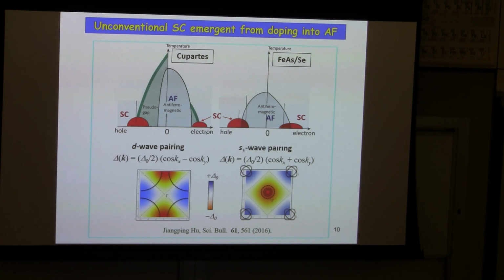Electron doping or hole doping are possible in both cuprate and iron-based materials. Another issue is that this superconductivity has a quite unconventional pairing symmetry. In the cuprate, many people know that the pairing is D-wave symmetry, which can be expressed as the momentum-dependent superconducting energy gap, cosine kx minus cosine ky. That is well known.